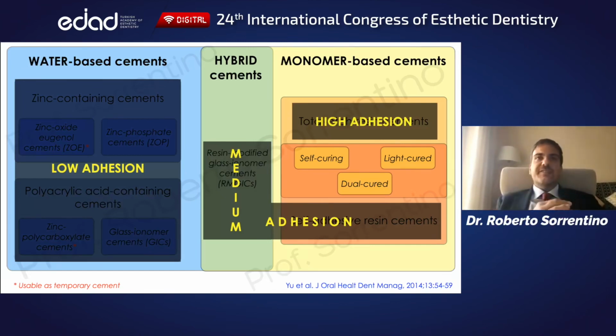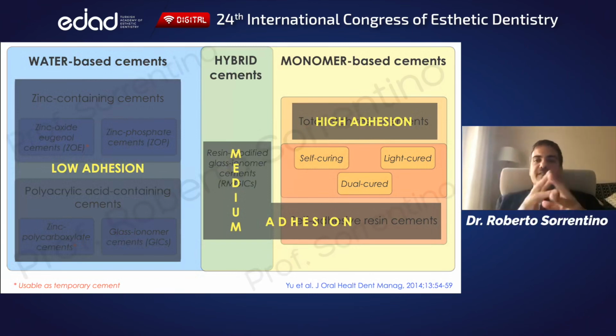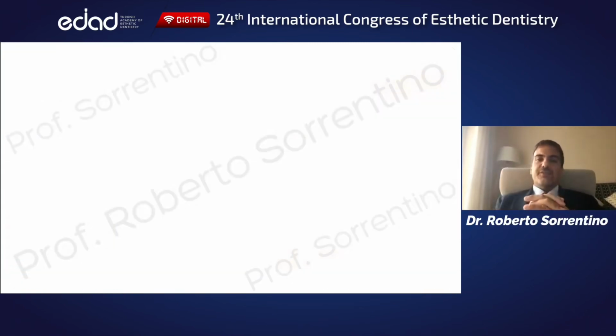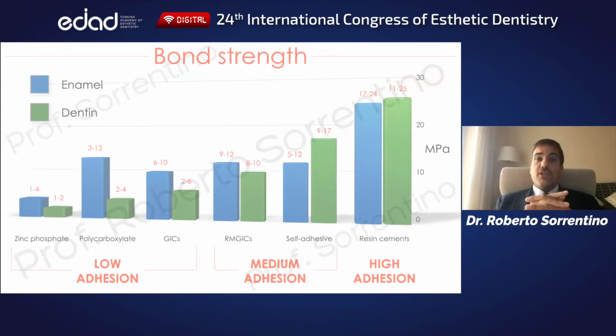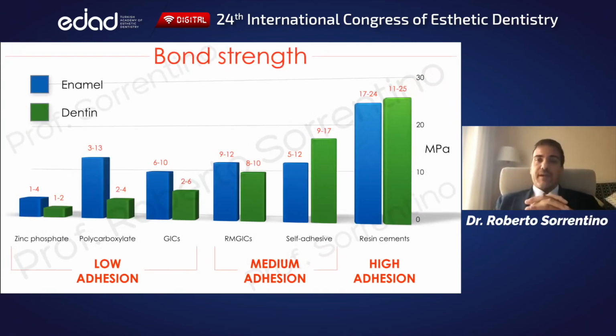As you can see in this graph, all luting agents present adhesive properties towards enamel and dentin, ranging from 1 to 2 megapascal for zinc phosphate to 25 megapascal for conventional resin cements. The bond strength is usually better in the presence of enamel, with the only exception of the self-adhesive resin cements, which show similar values on both substrates and slightly better results on dentin.